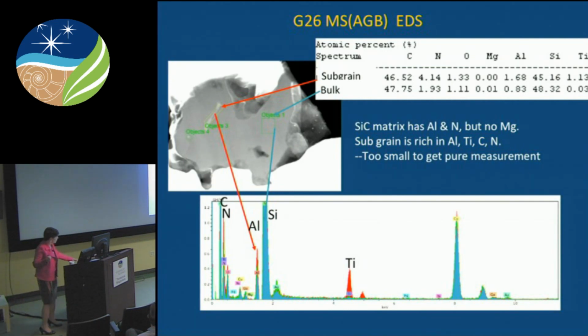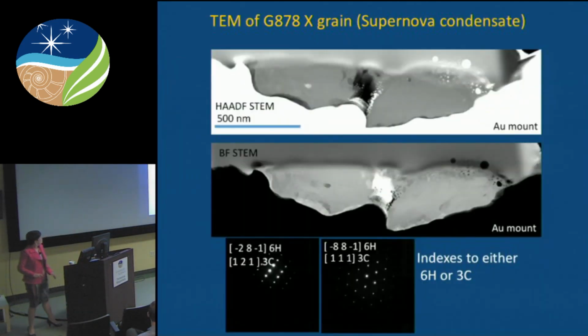So the bulk gets us something like 2 atom percent nitrogen, 1 atom percent aluminum, but the bulk is made up of stoichiometric silicon carbide. So we have definitely titanium, aluminum, nitride type subgrains. This other subgrain over here is actually rich in iron.